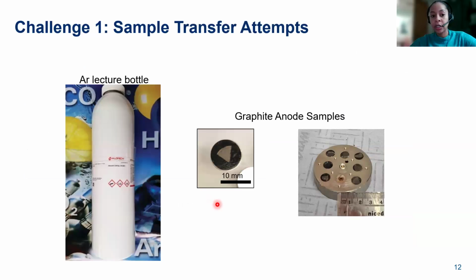So the first challenge that I faced was, how do I transfer the samples that were delivered in some argon-sealed bags into the NanoSIMS, which currently does not have an air-free sample transfer system? So the first idea was to take a lecture bottle that consists of argon and create a shielding gas as I took the sample, which is this graphite and copper tape that I then stuck onto the sample mount. So can we do that under shielding gas and then mount into the NanoSIMS sample holder, and then, under the shielding gas as well, transfer it into the NanoSIMS chamber? And that did not work. It was very clumsy. There was lots of air exposure. So we decided that that wouldn't work. There would be too much degradation and exposure to air and moisture.